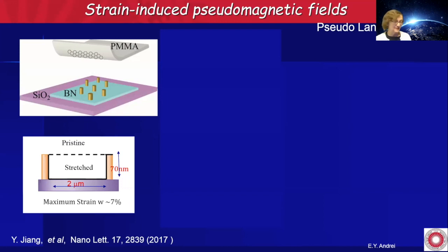Now, the buckling transition: we don't have too much control of the buckling pattern that you're going to get. So ideally, you'd want to have some control over it. So we started to do something to simulate the buckling. You can create a pattern of pillars here, and here we have gold pillars sitting on top of boron nitride, and then you can cover them with graphene.